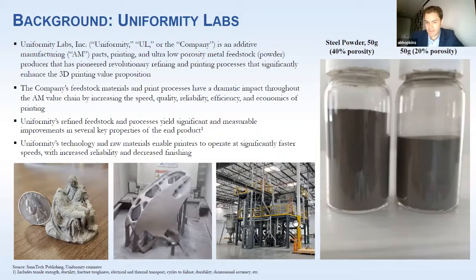That's a gas atomizer. That's how most powders are produced for these powder-based print technologies. That's Uniformity's gas atomizer. It's in Hayward, California. It's a big piece of equipment, but its goal is just to turn metal into nice spherical or roughly spherical particles of varying sizes. Again, that's Uniformity powder. This is 50 grams of powder. It happens to be 316L stainless. In each jar, you can see Uniformity powder is denser. Also flows really nicely. In jetting, it flows quite a bit more nicely. In other words, it has far less cohesion than other powders. And cohesion is very important to the spread and the uniformity of the spread on the bed. I'll get more to that later.